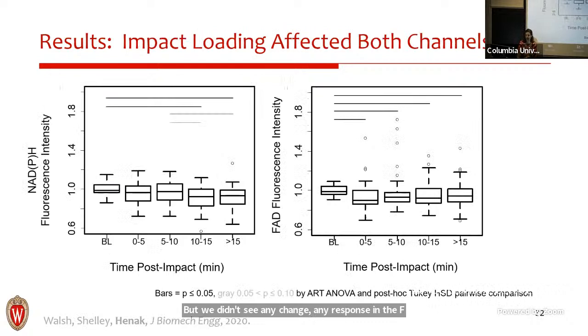When we did this impact loading, or this higher level loading at a faster rate with a really sharp tip, we saw a response in both channels. So here, again, we have time on the horizontal axis. I am actually showing the baseline values here. So that's the BL is the pre-loading case. For both NADPH and FAD, we saw a decrease in the response after impact loading. So that makes sense. We expect that we're influencing those cells.